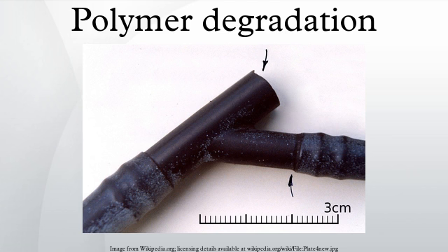The chlorine attacks weak parts of a product, and in the case of an acetal resin junction in a water supply system, it is the thread roots that were attacked first, causing a brittle crack to grow. Discoloration on the fracture surface was caused by deposition of carbonates from the hard water supply, so the joint had been in a critical state for many months. The problems in the US also occurred to polybutylene pipework, and led to the material being removed from that market, although it is still used elsewhere in the world.